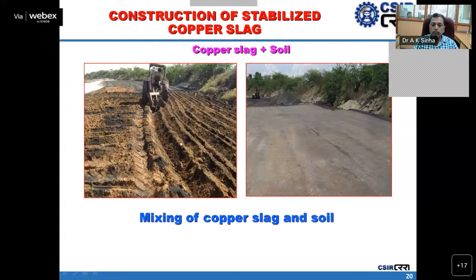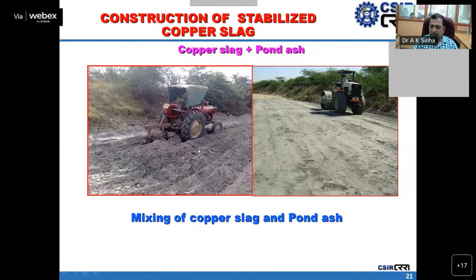So for mixing of copper slag and locally available soil, different indigenous equipment like tractor-towed disc, tractor-towed rotavator, and grader were used to know the efficacy of the mixing equipment. So it was found that the tractor-towed rotavator is efficient and it mixes properly. So this is the pictorial view of the copper slag mixed with pond ash, which is the mixing operation, and after compaction, this is the pond ash copper slag layers. And the whole embankment was constructed with copper slag and pond ash.